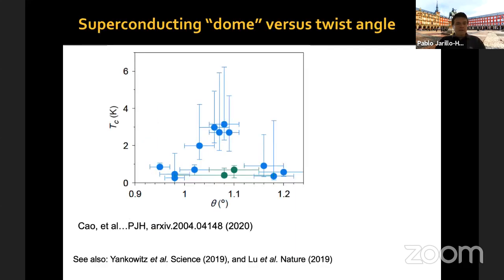Something that we've been doing recently is looking at what we mean by magic angle graphene. You could argue it is this 1.1 degrees, but actually it turns out there is a range of angles over which, for example, superconductivity happens, okay? We have been measuring several devices now, and we have quite a bit more statistics than I'm showing here. You can measure the critical temperature at optimal doping of the superconductor, okay? And you can see that as a function of angle there is also a dome of superconductivity, but now it is TC versus angle, not the usual TC versus doping. And this dome seems to be peaked pretty close to the original 1.1 degrees; between 1.05 and 1.1 degrees is where TC seems to be maximum, okay?